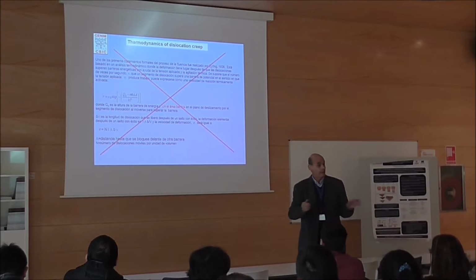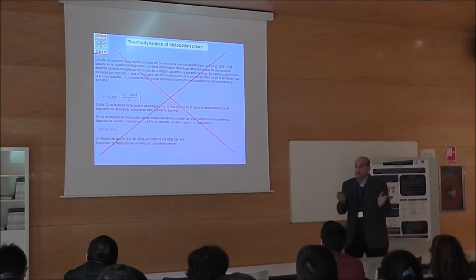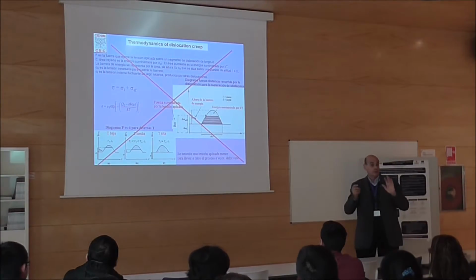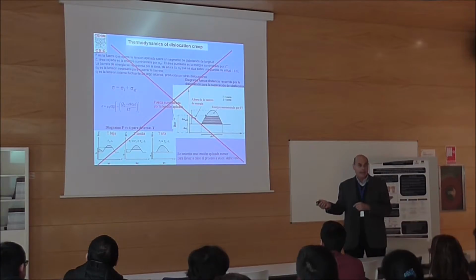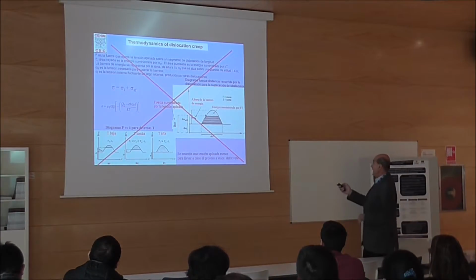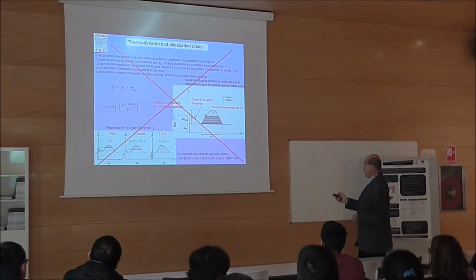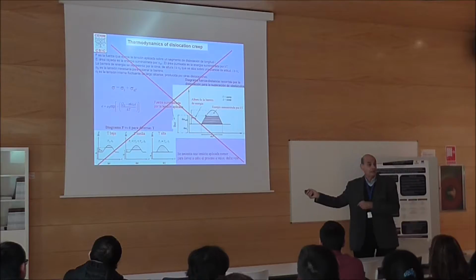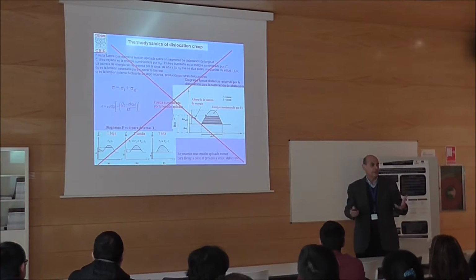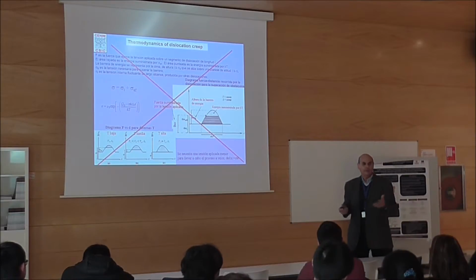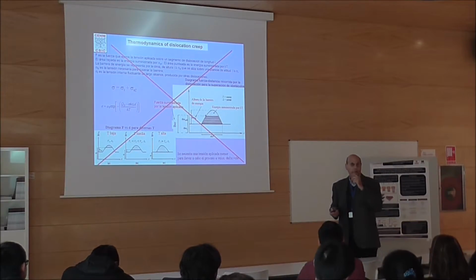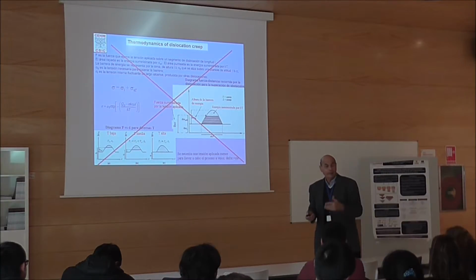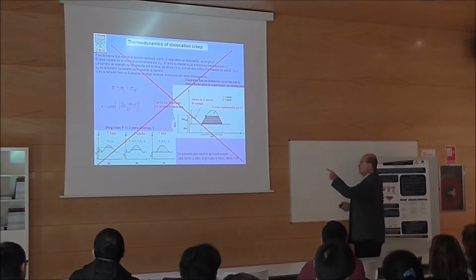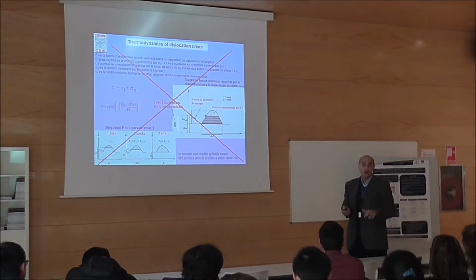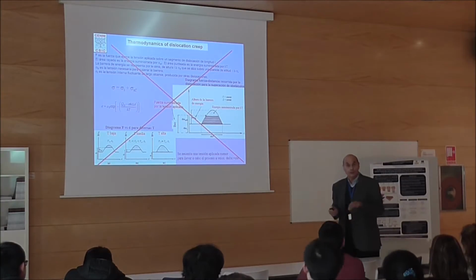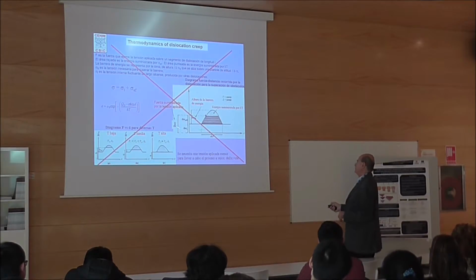I don't believe in that, so I'm not going to talk about this, and you have to go into other books to understand it. I'm going to talk about high temperature, where that will not apply. In my PhD thesis I had to use it, but I worked on titanium at 300 degrees. 300 degrees is 0.2 or 0.3 of the melting point, so it's quite a low temperature. It could be applied to low and medium temperatures, but not at high temperatures, and I'm going to talk only about high temperatures. And this is what you will see in the book.